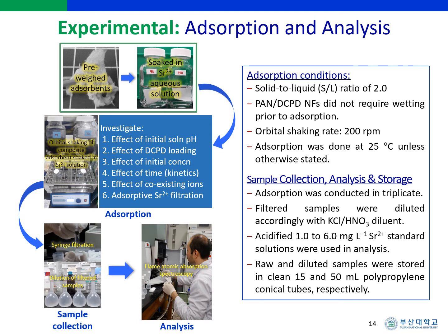Liquid samples before and after adsorption were transfer filtered in sample tubes using 0.2 micrometer cellulose acetate syringe filter units. Aliquots of the collected samples were diluted into aqueous solutions containing 1 times 10 to the 3 milligram per liter, or 1 times 10 to the 3 ppm, potassium ions from potassium chloride and 2.58% nitric acid, or HNO3, in polymethylpentene volumetric flasks.